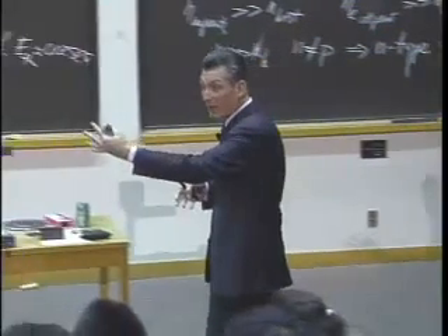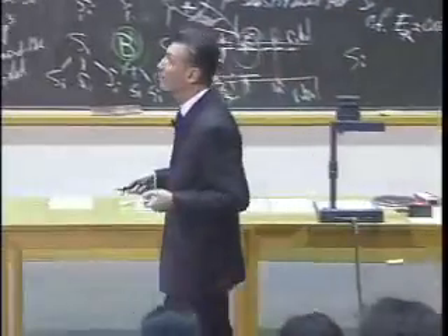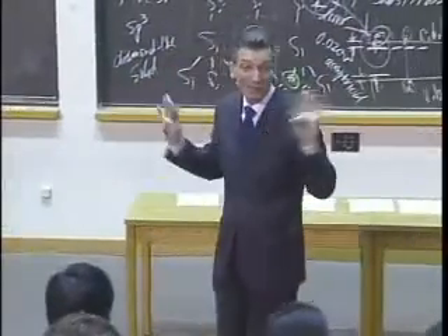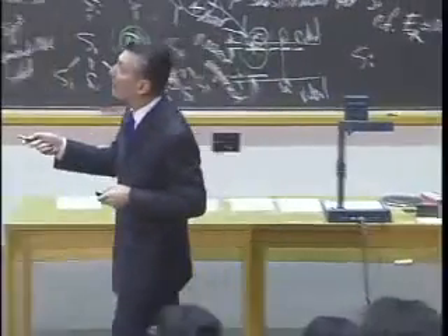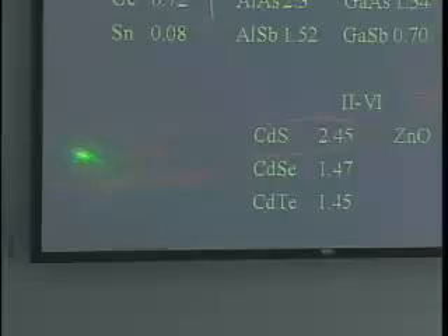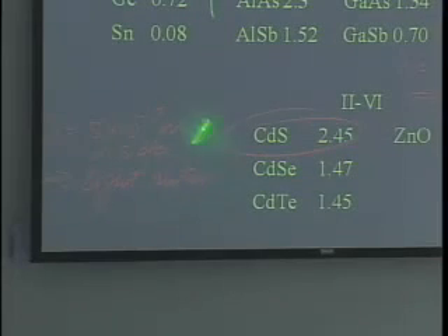And some of these are really interesting. Indium antimonide has a band gap of about 0.2 of an electron volt, which means that its absorption edge is 7 times 10 to the minus 6, 7 micrometers, which puts it in the IR. And this is one of the materials that would be used as a sensor for night vision. Because what are you really sensing when you're looking at night? You're sensing heat. You don't see the human body. You see the heat coming from the human body. All right? So if everything's cold and there's no delta T, you don't see anything. Over here, cadmium sulfide. Cadmium sulfide is 5 times 10 to the minus 7. That's right smack dab in the middle of the visible.